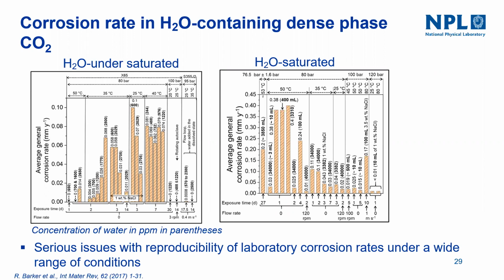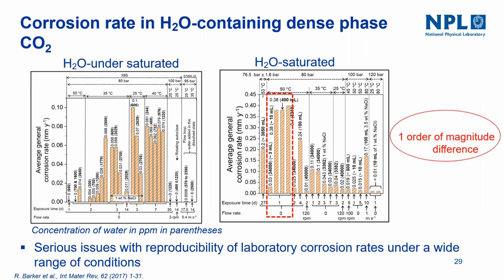This could be due to improper control of test parameters during testing. For H2O as well, it's very complex to compare because of varying parameters, but there is one condition where everything is the same, like 50 degrees centigrade, pressures, flow rates, and time, but there's a significant difference of one order of magnitude from one study to another. This is data from the last decade, so it is highly concerning. It is a very serious issue of reproducibility. It is very hard to compare one laboratory's tests with another's, and we can't deduce any reasonable conclusions based on flow rates, temperatures, or pressure.